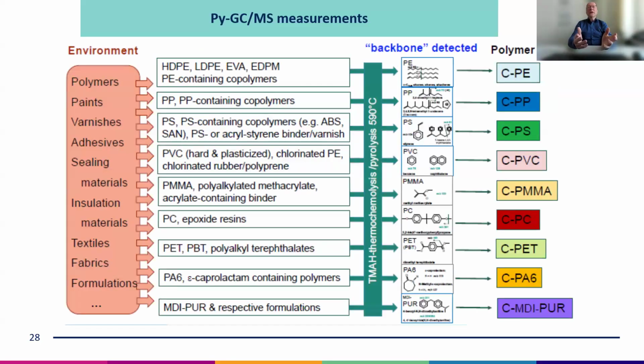Here are the clusters. That means you have an environment, also a food sample, ambient air, also polymers, paints, adhesives, and sealing materials. And then you see here which polymers are in the same cluster, and the clusters are also shown on the right side, because only for these 10 clusters we have indicators. The advantage of this method is that you can also identify tire wear particles.